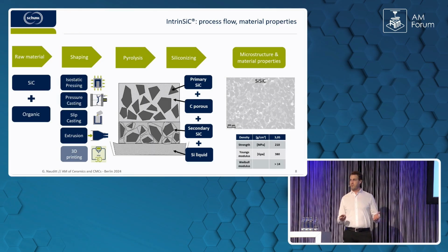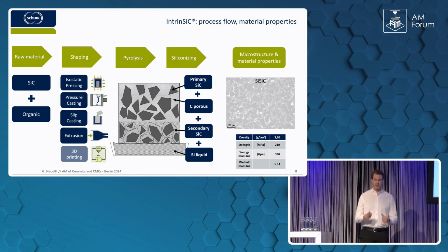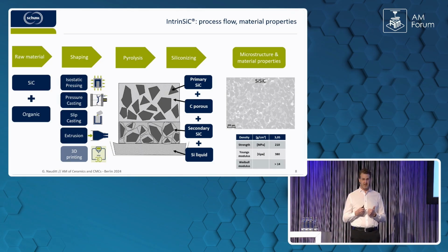So what is then done afterwards? We do a pyrolysis of the printed part. In the pyrolysis, the binder is converted from the organic into a porous carbon. Fabia already explained it. Then there takes place a siliconizing. That means the melted silicon gets inside of the part by capillary forces and reacts with the present porous carbon and forms a secondary silicon carbide around the primary silicon carbide grains. And this leads us to the right-hand side to the microstructure where we have dark gray grains. This is the primary silicon carbide, our powder.